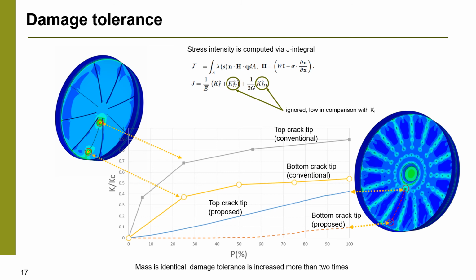prevails. So we compute it for two crack tips, and in the plot we calculate the ratio of stress intensity factor to the critical one for all crack tips, depending on the level of pressure load. And it can be concluded that since we have structures of identical mass, the damage tolerance is increased in the proposed structure about 2 times.